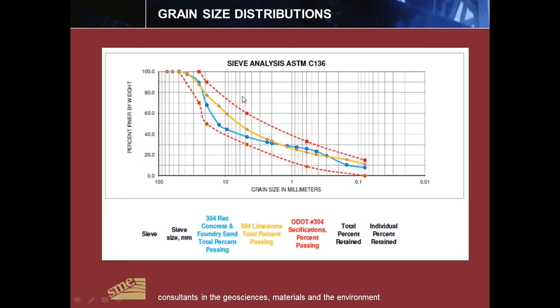The final combination of materials shows the ODOT gradation, with the upper and lower bounds for the gradation in red. The yellow or orange curve here is the ODOT limestone material, showing a pretty well-graded material with less coarse aggregate in it than our blended material has. So our blended material had a little bit more top end sizes in it and was cleaner than the standard 304 material that we used.